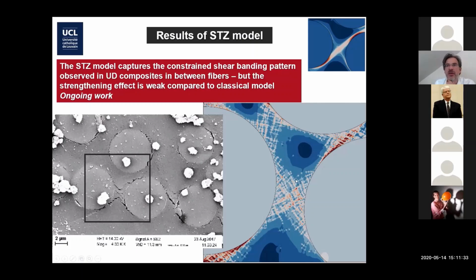We have not yet addressed this point, and you're right. In this 1 or 2 micrometer channel between the two fibers, we certainly know that the sizing that is put on the fibers, reacting with the matrix to get good adhesion, is affecting the chemistry and the molecular structure over a size that AFM measurements have shown to be on the order of hundreds of nanometers. So there is certainly a transition zone here, an interface region where the properties should be different, also perhaps the chain alignment. So there is certainly something there, and something on the other side, which is a decent fraction of the volume.